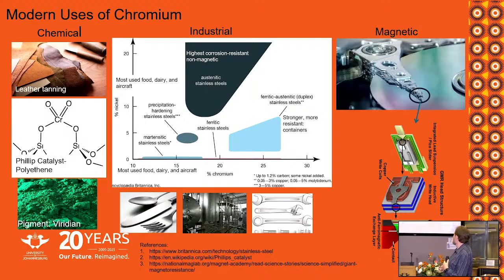Actually, chrome within this chemical structure seems to sit in the silicon oxide gel, if you do a little bit of the study. But it's mainly to manufacture plastics: this catalyst is used to make the base material for plastic. And of course, the pigment, chromium oxide.